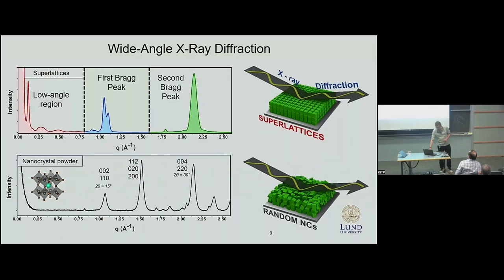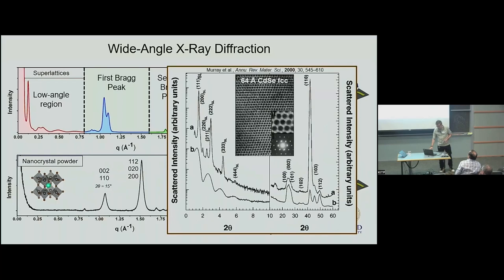Again, this was very different than what we were used to based on cadmium selenide. For example, here's data from one of the Chris Murray papers, where once they form an FCC superlattice of cadmium selenide, at low angle you see superlattice reflections, but at high angles you see only preferred orientation effect without any fine structure on the Bragg peaks.